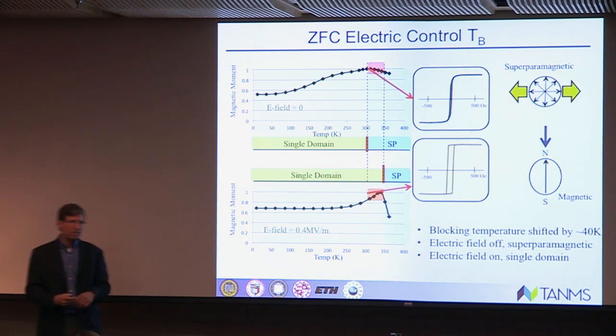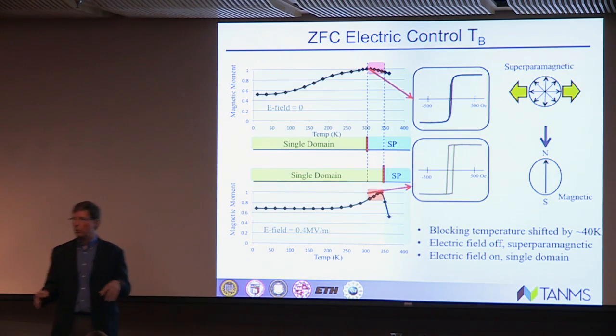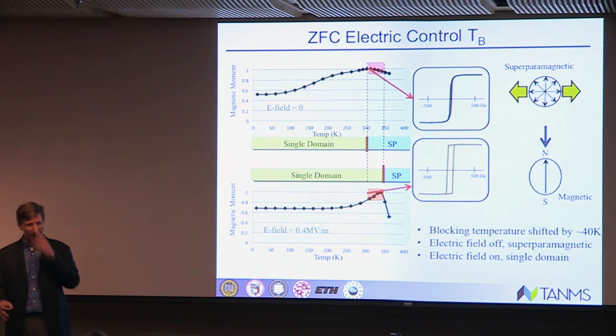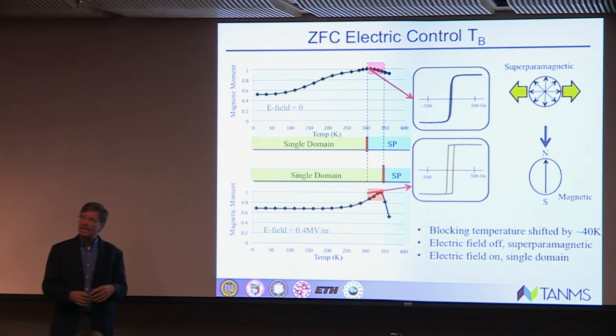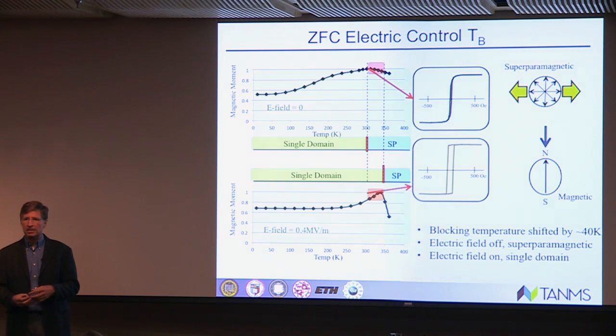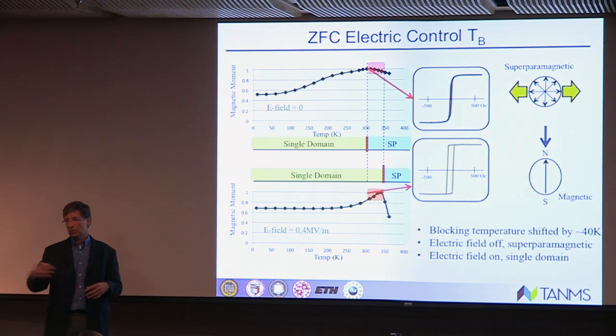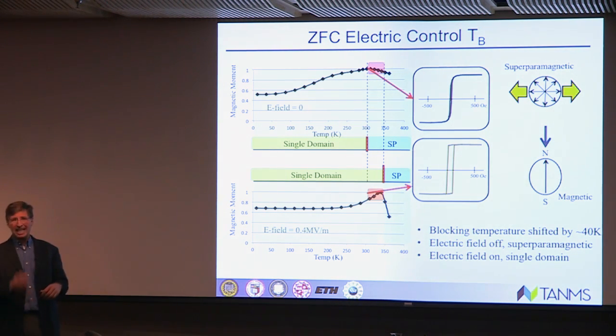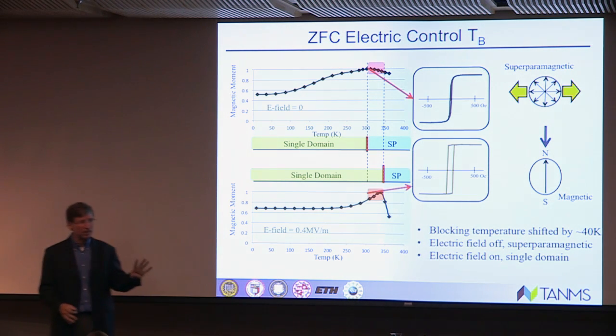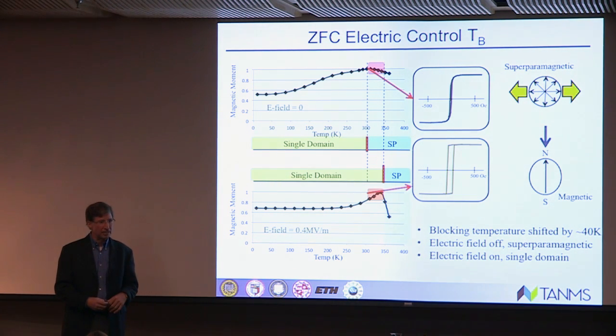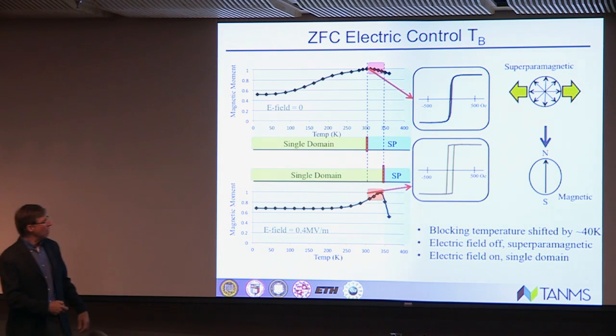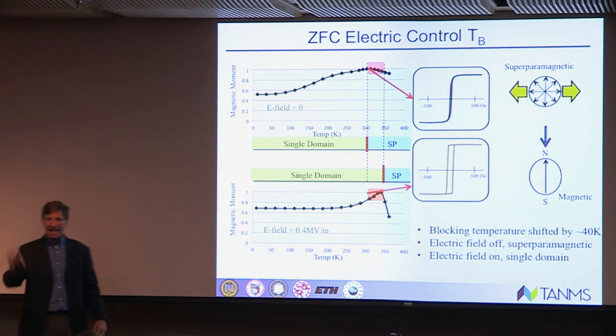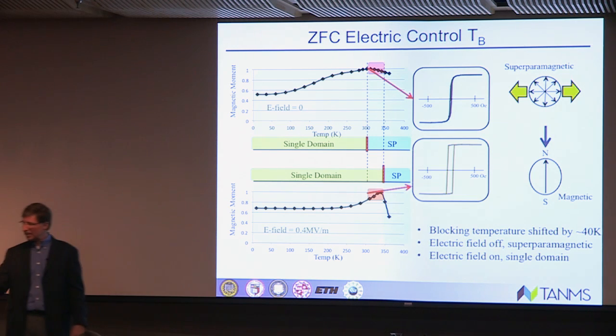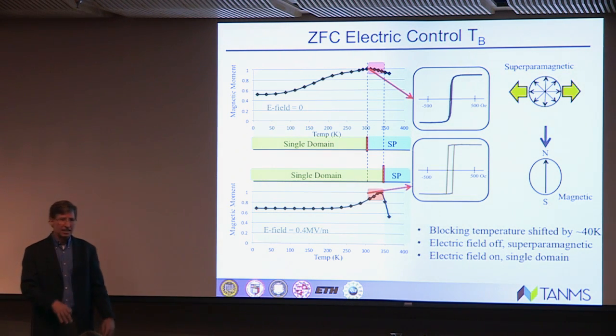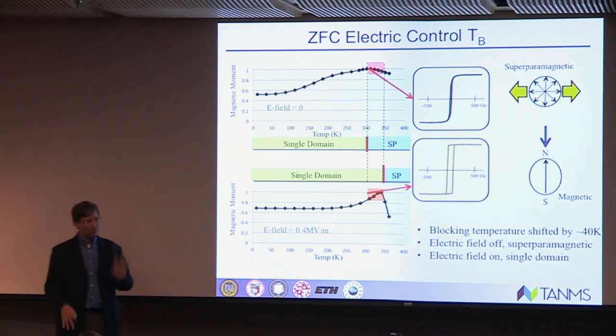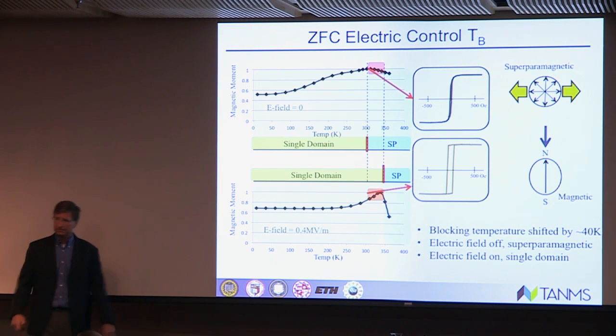Now the one question some people ask me is, well, can you shift it more than 40 degrees Kelvin? Yes, we can. Why? I told you in the beginning, nickel is not the best magnetoelastic material. If you choose other materials like Terfenol-D, you should be able to increase that shift in blocking temperatures from 40 degrees Kelvin to something like a couple hundred degrees Kelvin. And you may ask, how close was this to an analytical prediction? Our analytical prediction said it should shift about 46, and we measured about 40. So we think we're very much in the ballpark at that point.